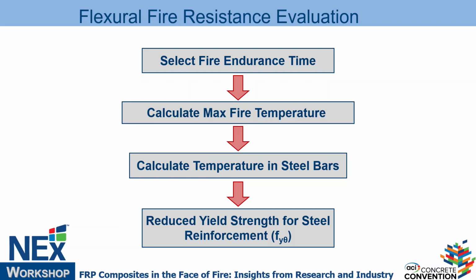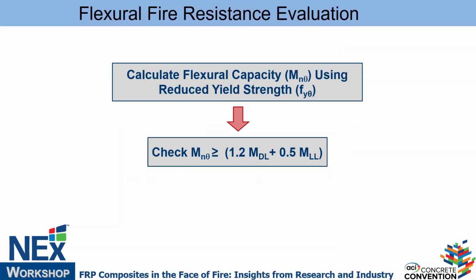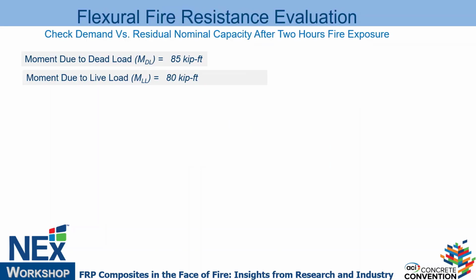And we went through the same process that I mentioned to you, right? We calculate the maximum temperature, which is ASTM E119. We know what the temperature is at 2 hours, right? So we take that temperature and run it, either by curves, through 216, or through modeling, and calculate the temperature of each bar, and then calculate the yield for the higher temperature, and calculate the capacity, and compare it to the demand during fire of 1.2 dead, 0.5 live. So these are the numbers for that specific beam. The dead load was close to 85, live load close to 80.